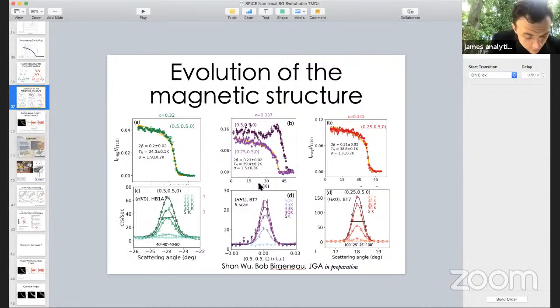It's a really good question. The initial motivation for looking at the structure was because of the broken inversion, but it was mainly to get the spin Hall effect, mainly to get the Edelstein effect to work. We wanted the current to be slightly spin polarized. So that's why we chose this structure. How it affects the magnetic structure, as I said, we've done some extensive DFT, and you really only get these two nearly degenerate ground states, the stripe and the zigzag.